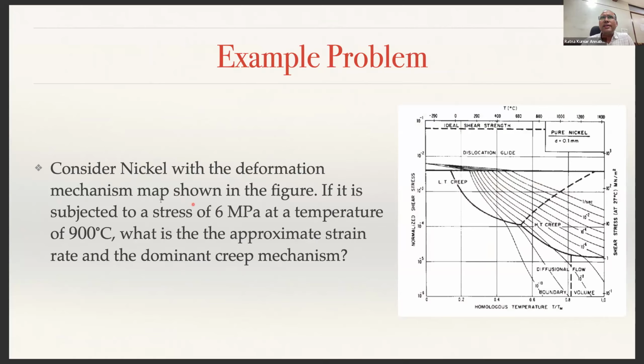So if you take a nickel specimen with a deformation mechanism map as shown in this figure, subjected to a stress of 6 MPa at a temperature of 900 degrees Celsius, you need to know the melting temperature of nickel. Let us say the homologous temperature is about 0.6 and it is subjected to a stress of 6 MPa. So you need to compute the corresponding normalized shear stress, with the shear stress measured at room temperature. Corresponding to that, you can look at the homologous temperature and that will give your shear strain rate.